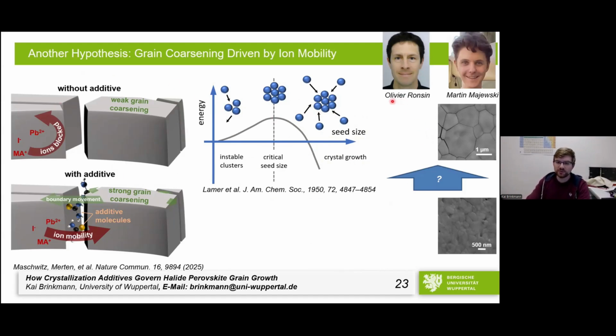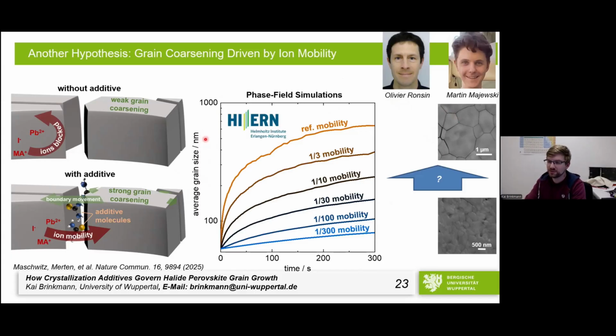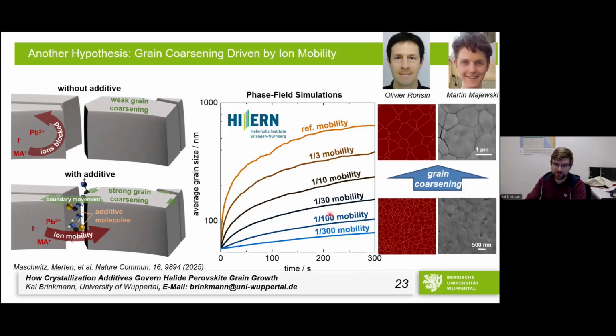And lucky us, we ran into Olivier and Martin, who were studying perovskite coarsening for a while now already. And they looked at our data and said, hey, wait, this looks a lot like a coarsening. Chemists know this as Ostwald ripening. So it's basically the redistribution of grain boundaries if you give them enough time and enough mobility. So the mere fact that the grains do not want to exist in small grains, but that they want to grow in order to reduce the amount of grain boundaries. And if you basically just take a textbook coarsening approach, give them a little bit of variations, you end up with this kind of behavior, and you end up with these kind of distributions for a material where the mobility of the grain boundaries, which in our case actually translates to the mobility of ions across the grain boundaries, is very low.